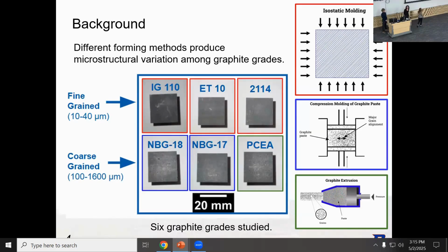As we see here among our 6 different grades, there were several different forming methods used to create these graphites. If we look at the top, the ones that are outlined in red include IG-110, ET-10, and 2114. These were all formed via isostatic molding, which is a uniform application of pressure on all faces of the graphites. This resulted in relatively fine-grained microstructures between 10 and 40 micron grain diameter.